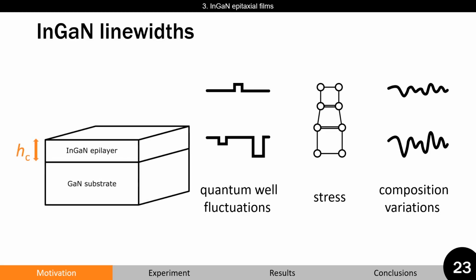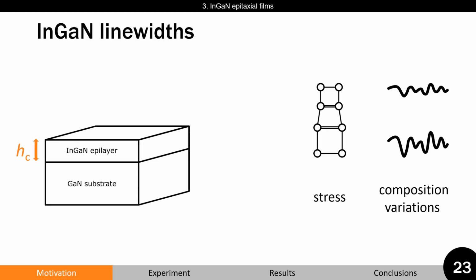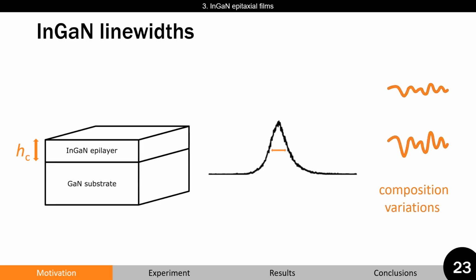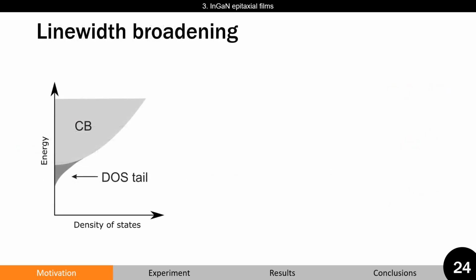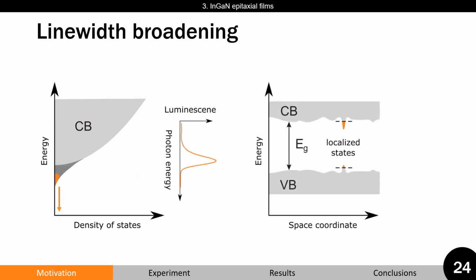Having epilayers instead of quantum wells allows excluding quantum well width fluctuations. Growing layers below the critical thickness, in other words, having them strained, allows avoiding stress relaxation induced processes. Thus, we can study how photoluminescence broadening is directly affected by composition variations. One should mention that photoluminescence provides information only about the localized states introduced due to broadening. Absorption measurement is a more correct way to study all extended states.